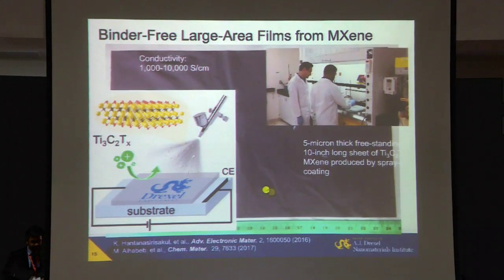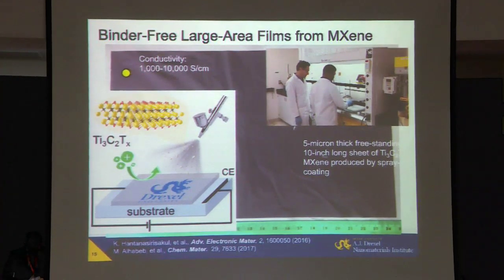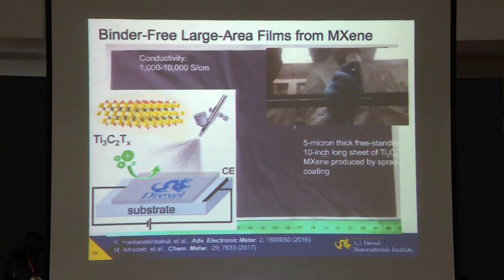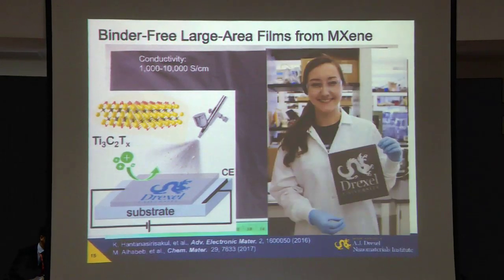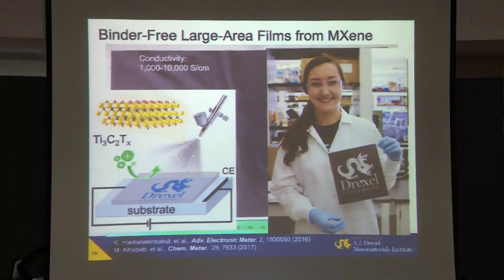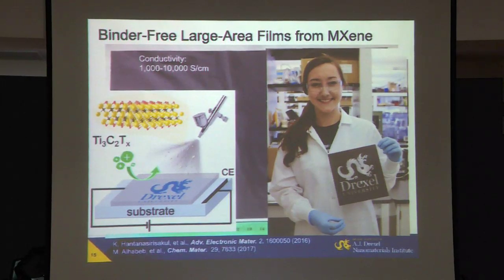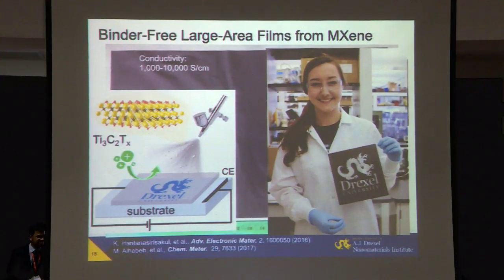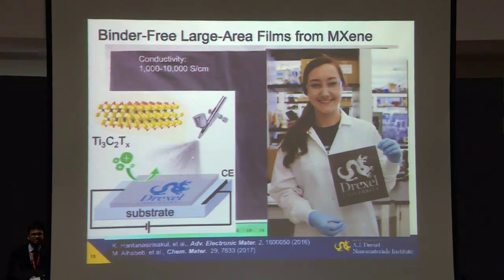You can see it's 5 micron thin, but it's freestanding and separate from the surface. And depending on the amount of graphene, in this case, we had about 1,000 to 10,000 Siemens per centimeter. Actually, the more graphene, reduced graphene oxide, you add, the lower the conductivity, but we need it for energy storage purposes. And this is another student, Kathleen Maleski, holding a Drexel University logo, spray coated. So again, nanotechnology does not need to be nano quantity or billion dollars worth in expenses to build it here.